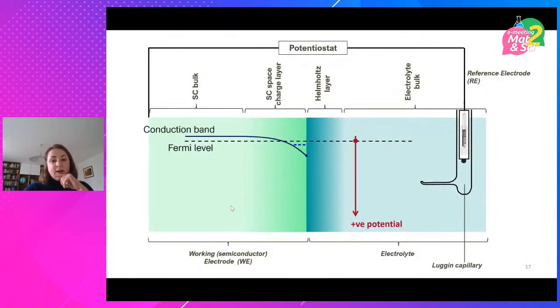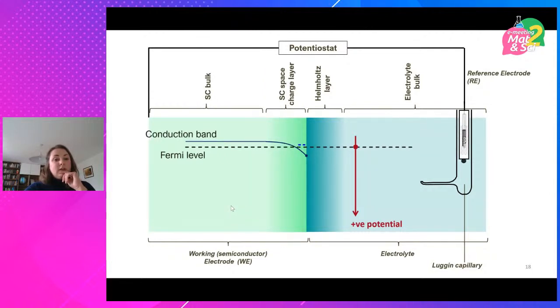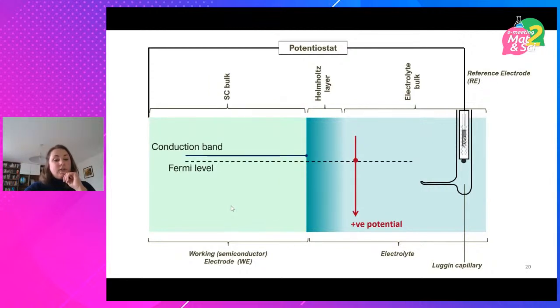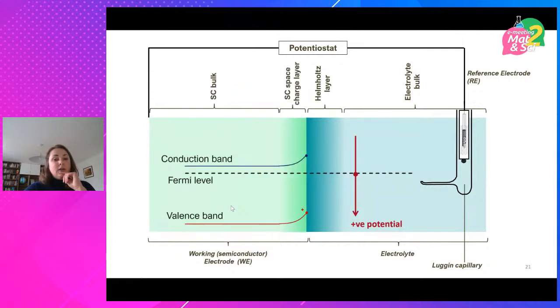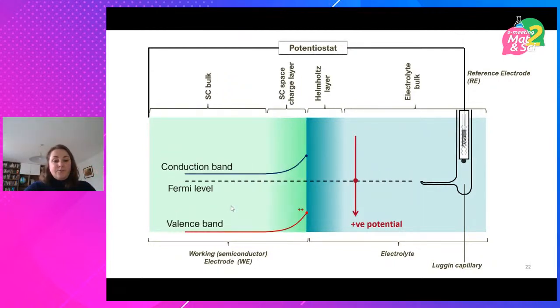So in this scenario, you have a working semiconductor electrode and then an electrolyte. Then you have the bulk of the semiconductor, the bulk of the electrolyte. And then you have those interfacial regions where things are different. So you've got the semiconductor space charge layer and the Helmholtz layer. So the question is, what happens in the Helmholtz layer? What happens in the space charge layer, for example, is if you have, let's say, an N-type semiconductor, the bands are bent downwards, so you've got accumulation of electrons. When you gradually bend the bands downward, you pass through a stage where there's no band bending. That would be the flat band potential. And then you bend them the other way and you start to have depletion. So this is the condition at which you have oxygen evolution happening on N-type semiconductor electrodes.